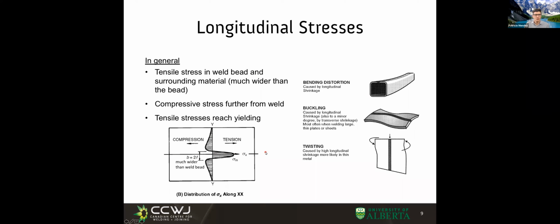this is a typical distribution of residual stresses from a book, and it says right near the weld there are going to be very high tensile stresses, and then outside the weld we're going to have, guess what, the compressive stresses that balance out the tensile stresses, right? Something I want to bring to your attention. Me, myself, until not too long ago, I used to think that the part that ended up in tension was just the molten part, the weld bead. So let me dispel that.